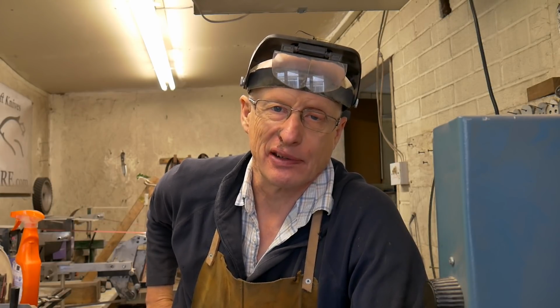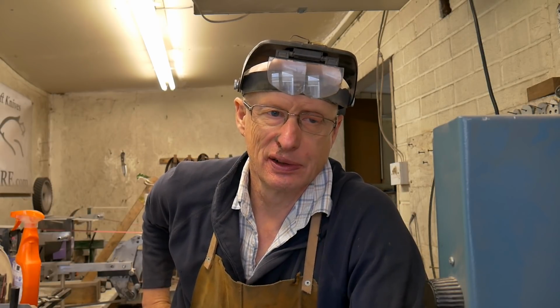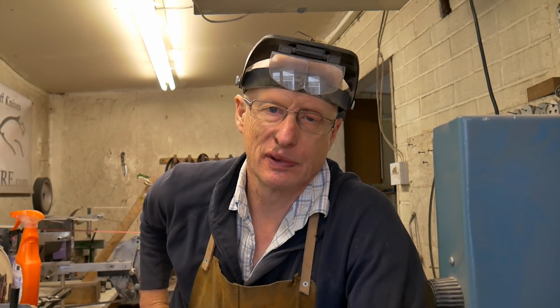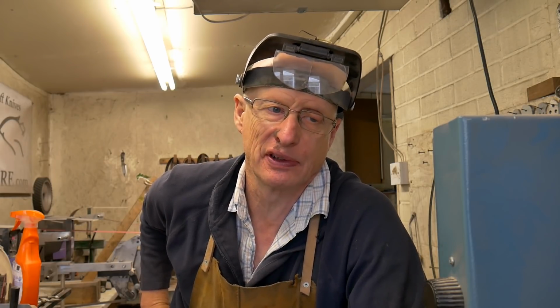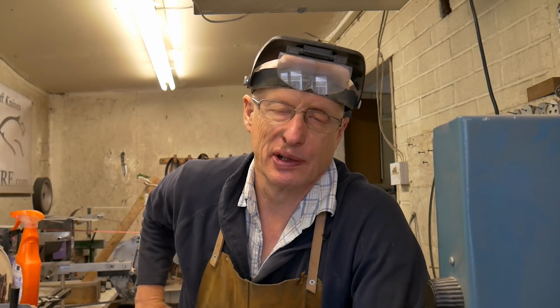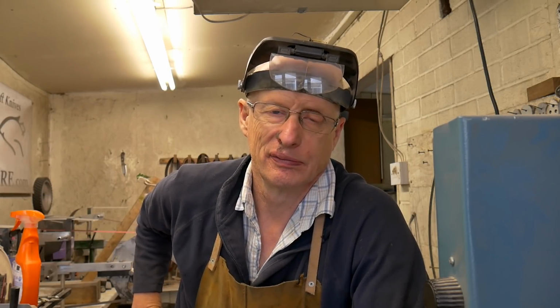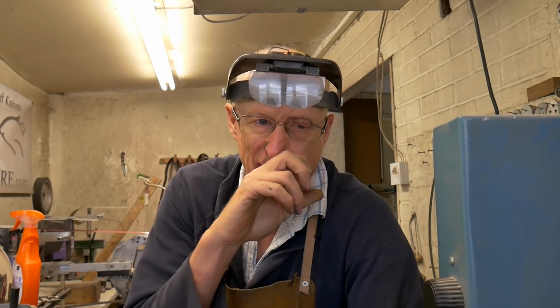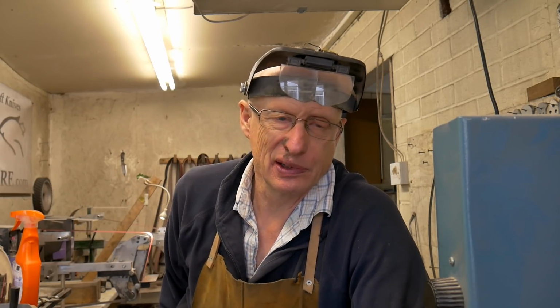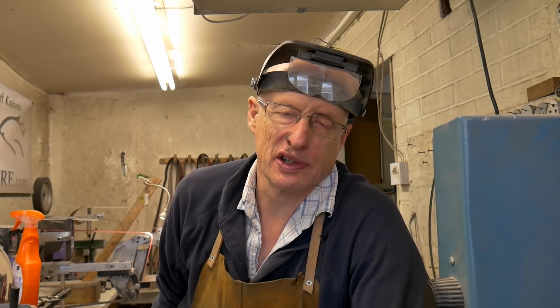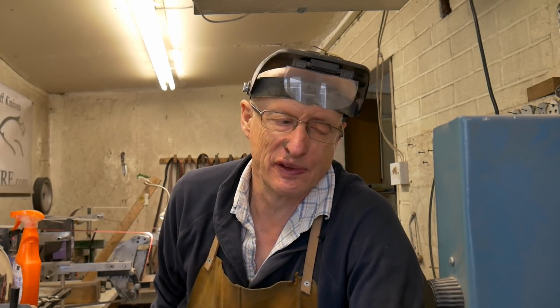In this video I'm going to talk about how do you know how good your heat treat really is. I've got a Rockwell tester, so I test all my blades for hardness after I've quenched them, and I also test them after I've tempered them, so I know where they are on the scale. And I know that generally 59 HRC gives you perhaps an optimum hardness for a Scandinavian grind knife.